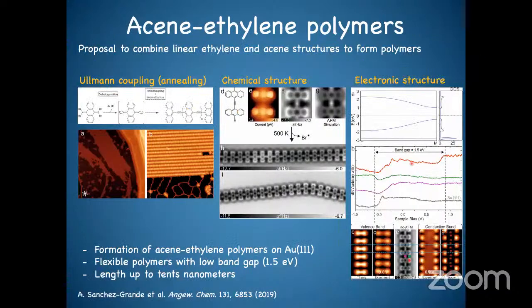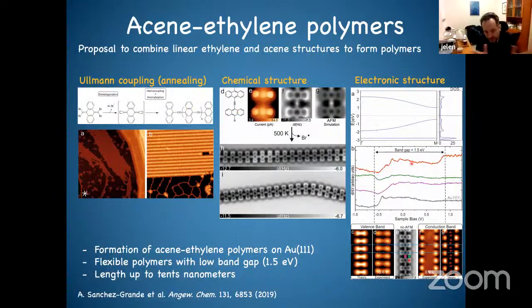Yes. Okay, so let's now go to reality. We talked to chemists, and the chemists from Spain provided us these precursors. So it's like anthracene, there are two bonds, and then you have two bromines here. And that's a very well-known reaction on the surface: when you put this kind of halogen-terminated molecule on a metallic surface, you anneal them. First, what you will see is the carbon-bromine bond break. You will create a radical, and then if you are lucky, these radicals will interact with each other. And that's what we see from the microscope.